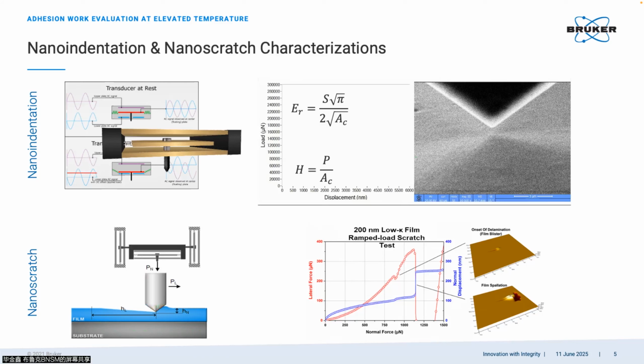So we will typically have two different segments. One is the so-called loading segment. The other one is the unloading segment. If there is some plastic deformation, you will have non-overlapping loading and unloading curves. And going through some analysis, we are able to convert the applied force versus penetration displacement into two mechanical properties, just as I mentioned previously. One is modulus for elasticity. The other one is hardness for plasticity.